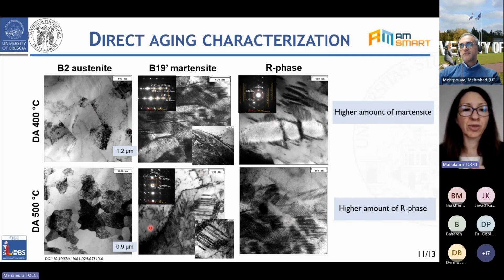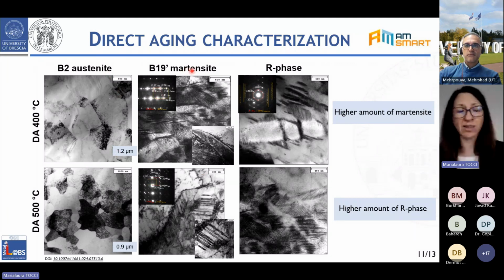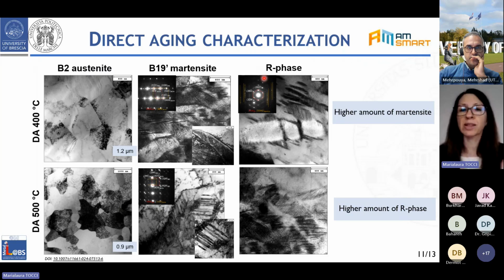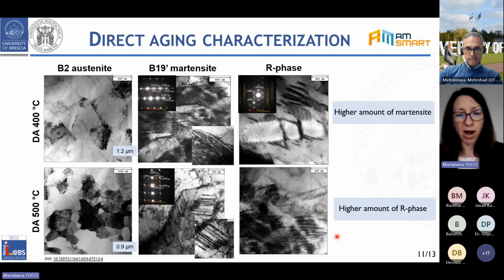In both cases, we can observe the presence of these, let's say, mixed structures. So we have austenite, we have martensite, as already mentioned, and from diffraction analysis, it was possible also to identify the presence of the R phase, the one that we inferred from the results from the DSC analysis. Comparing the two treatments, it was found that after the DA400 treatment, there's a higher amount of martensite, in agreement with the results from the DSC. While if we increase the temperature of the aging, we have a higher amount of the R phase, this intermediate